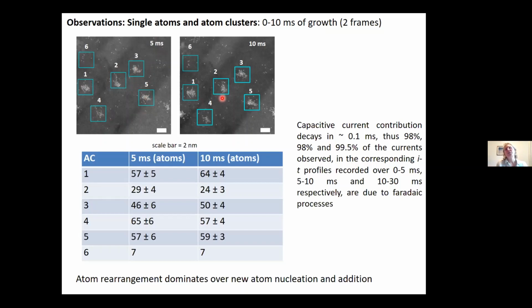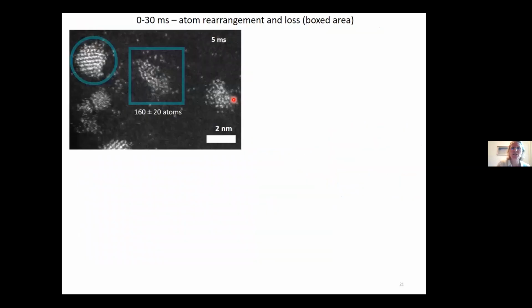And actually, we found in this particular image, and this is not to say what's going on in other areas, and I'll show you that none of these were really growing significantly in atom number. Really, what they were doing was, almost under that potential field, undergoing a rearrangement. Growth was occurring in different places on the surface. So this was interesting to us. However, it gets really interesting when you start to look at more detailed pictures of the surface.